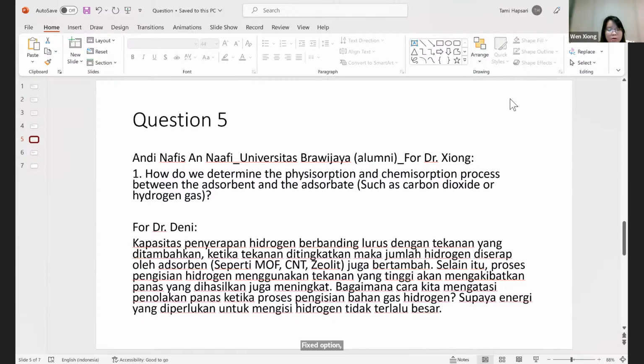That's how we generally determine physisorption and chemisorption. If you have both physisorption and chemisorption on one sample and you really want to see the difference, you can do some control experiments. For example, using our 3Flex, you can dose CO2 or hydrogen to the sample and see how much gas has been adsorbed at a certain temperature, let's say 20 degrees C or 0 degrees C.